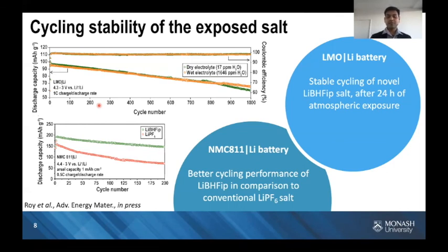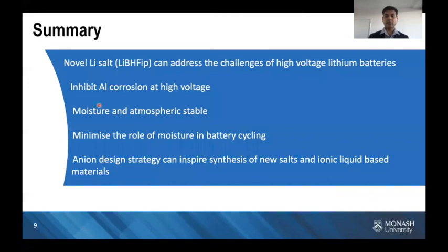So to summarize, here we have a novel lithium borate salt, which can address the challenges of high voltage lithium batteries, including inhibiting the corrosion tendencies of aluminium at high voltage. And we have also seen this salt to be quite stable towards moisture and atmospheric conditions. And not only that, it also helps to minimize the presence of moisture in a lithium metal battery. This particular salt, we have found to have properties which are highly relevant for high voltage applications. Therefore, the anion design strategy adopted in this work can inspire the synthesis of novel ionic liquids and associated salts, which I believe can perform much better in higher voltage batteries for their longer term stable cycling.